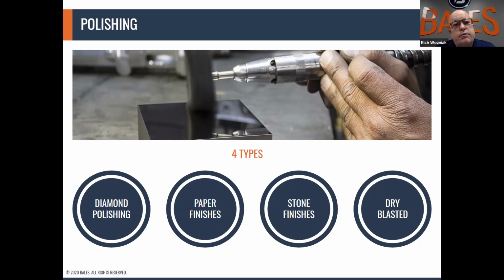Also, there's dry blast, which is D1 through D3, which goes from a number 11 glass bead to the two different types of aluminum oxide blast. What's nice about the dry blast, especially if you have a non-show component with some areas that may not look right cosmetically, is that a dry blast with aluminum oxide will definitely help smooth those lines and give you a refined inner detail. Or if you get a little ding during a process, you can easily stone it and then give it a little blast finish, and you would never know. Those things do happen on occasion.